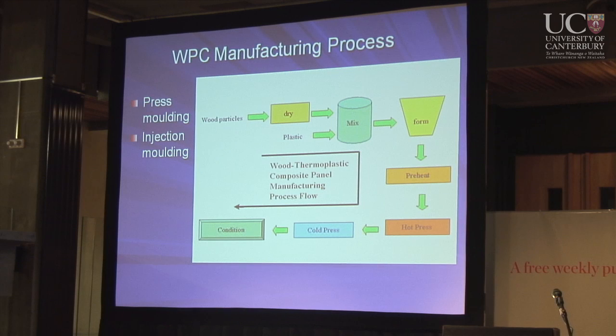For the processing of our product, normally you can do the processing through either press molding or injection molding. The current wood plastic composite in the market is mainly made through injection molding. And we developed a technology using press molding. We first mix the wood particles and the plastic together through a compounding machine, and then we put it in the hot press to form a sheet. Of course, you can make more complicated shaped products using the hot press.